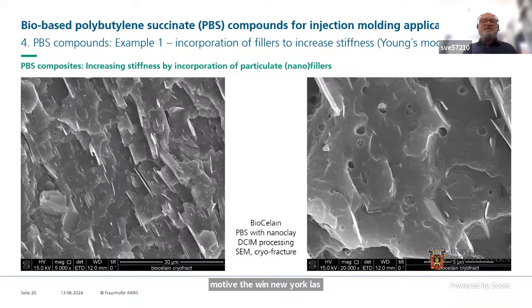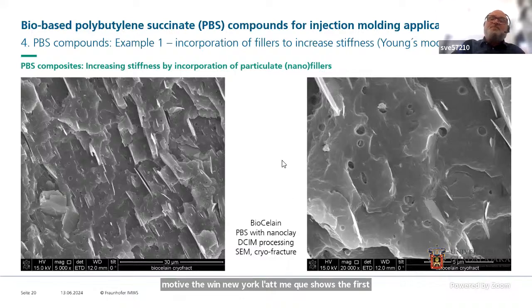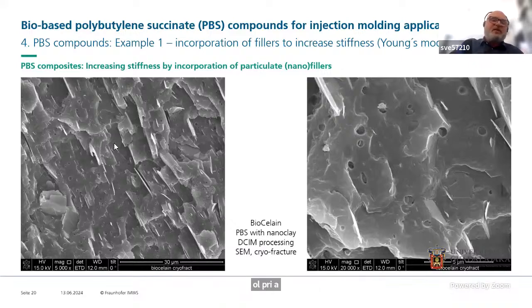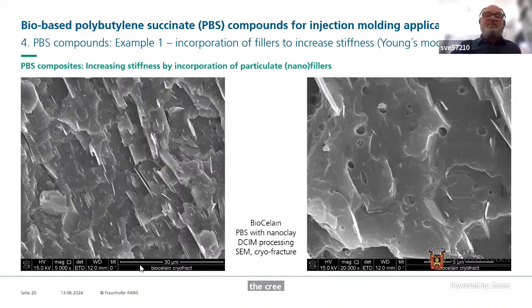This is just the first example, a very classical approach where we use nanofillers, for instance, a layered silicate material, which is, of course, not a bio-based material, which is a very conventional material, to incorporate the nanofillers here in the PBS to increase the stiffness. A very simple thing, that is the BioCelain, that is the cups that I have over here, these beautiful items that are really of a fantastic grip, of fantastic properties.